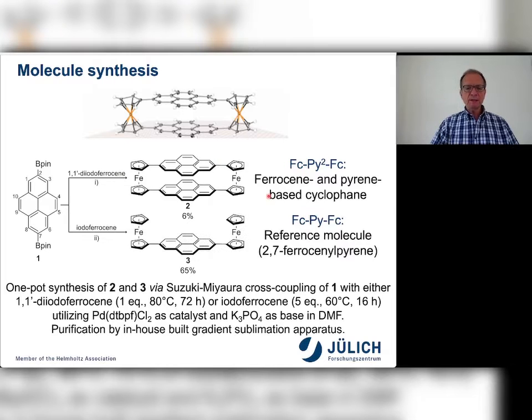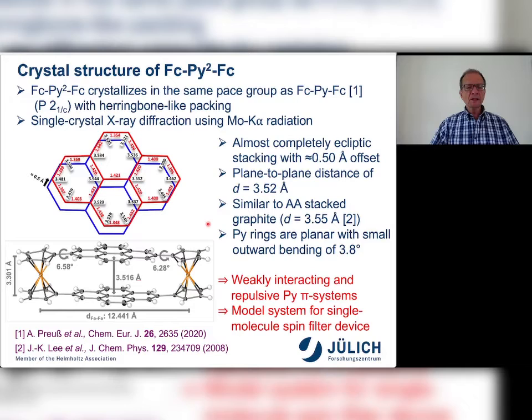We have also synthesized a very similar molecule where only the upper pyrene part is missing, and I will call this the reference molecule. We have then performed a crystal structure analysis by X-rays, and we found that the cyclophane crystallizes in the same space group as the reference molecule, which has been reported only last year in this paper. The analysis also shows that the pyrene parts indeed have almost completely eclipsed stacking with just a small lateral offset